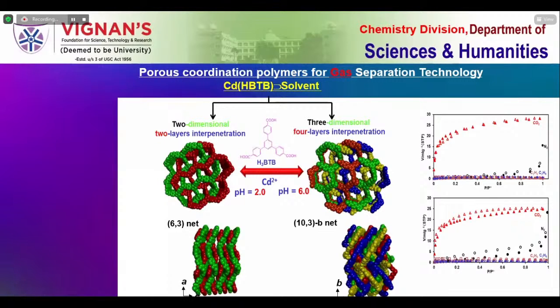We can possibly get two different kinds of compounds at two different pHs. For example, if we use a highly acidic condition like pH 2, we get this kind of compound, which is a two-dimensional layer interpenetration, because the layers are interpenetrated to each other. The importance of this interpenetration is that we have very small pores. Sometimes small pores are also very important. We know that porosity is useful, but sometimes we need small pores, especially for separation of gas molecules. Whereas the other one is a three-dimensional